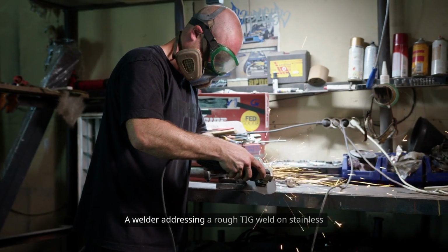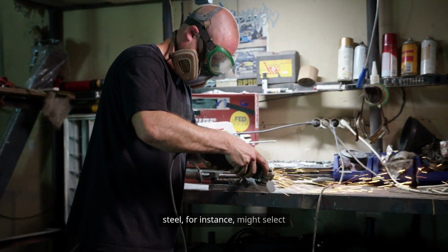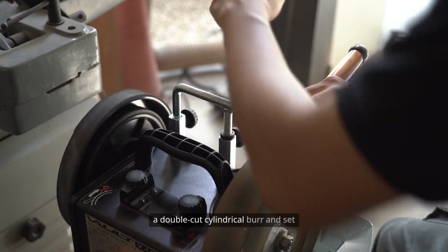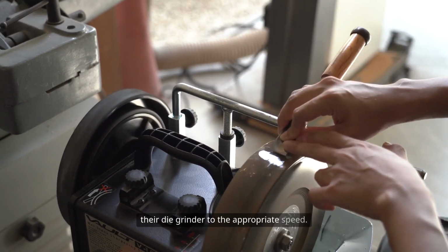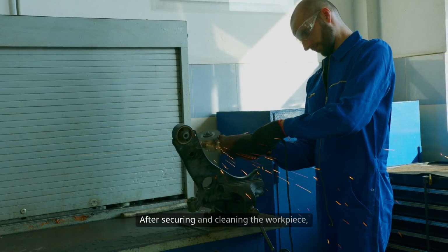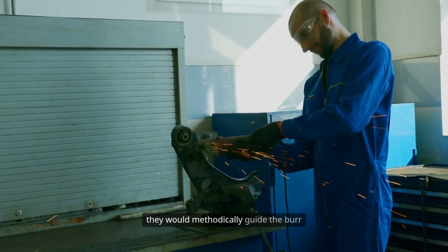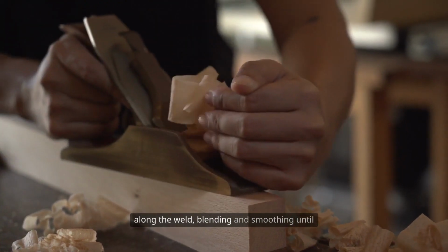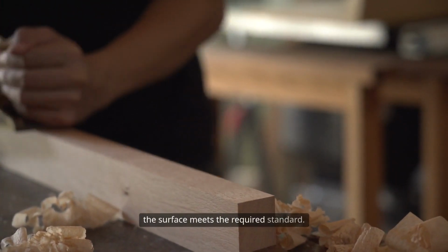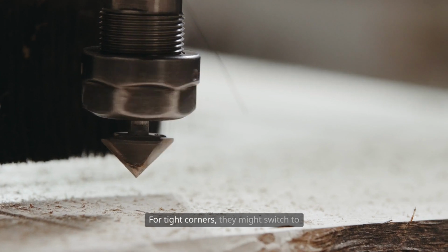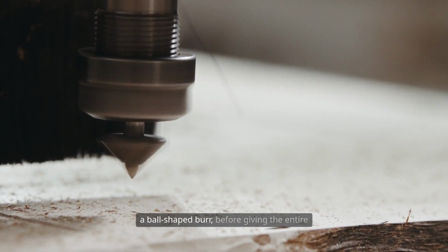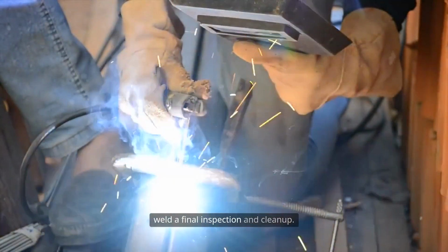A welder addressing a rough TIG weld on stainless steel, for instance, might select a double-cut cylindrical burr and set their die grinder to the appropriate speed. After securing and cleaning the workpiece, they would methodically guide the burr along the weld, blending and smoothing until the surface meets the required standard. For tight corners, they might switch to a ball-shaped burr, before giving the entire weld a final inspection and cleanup.